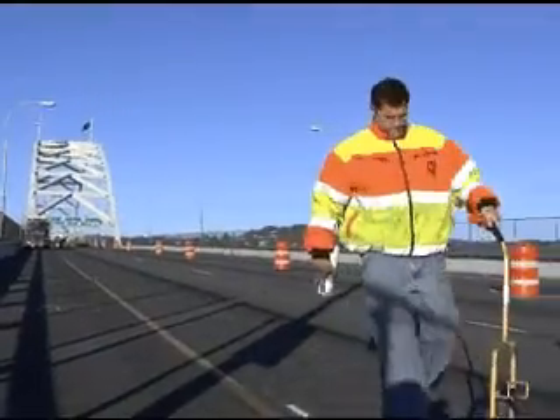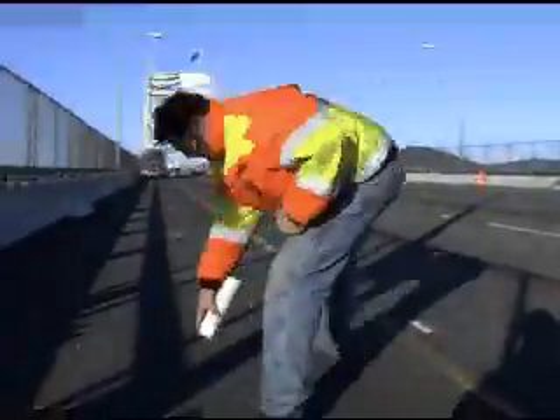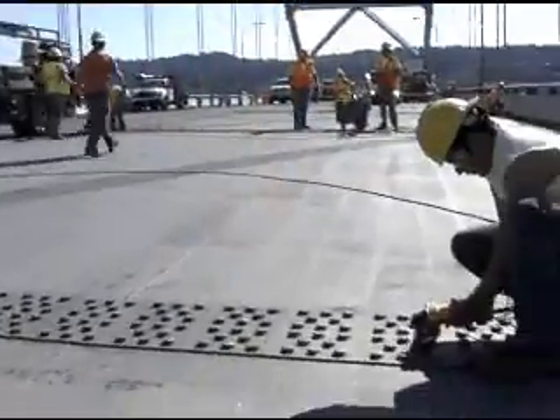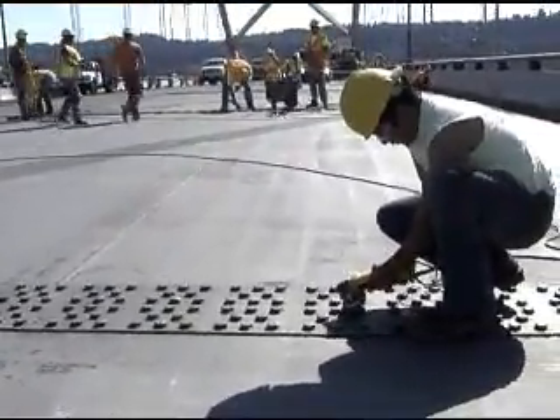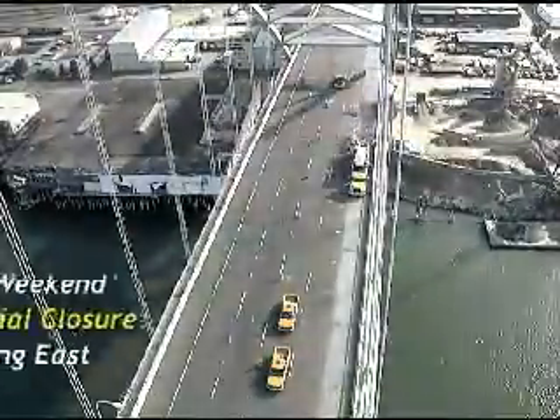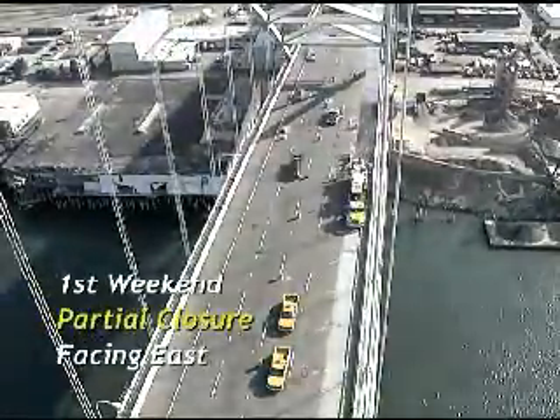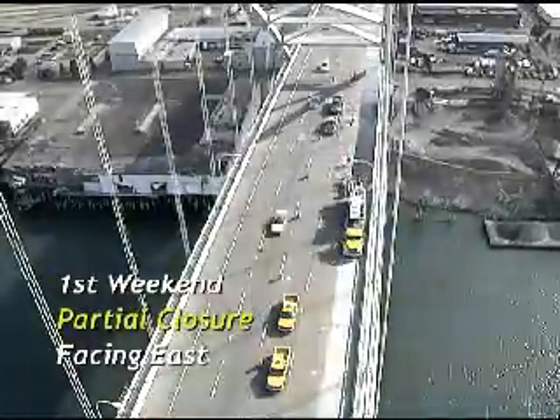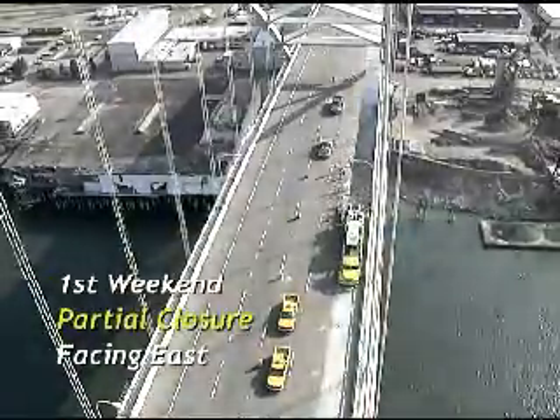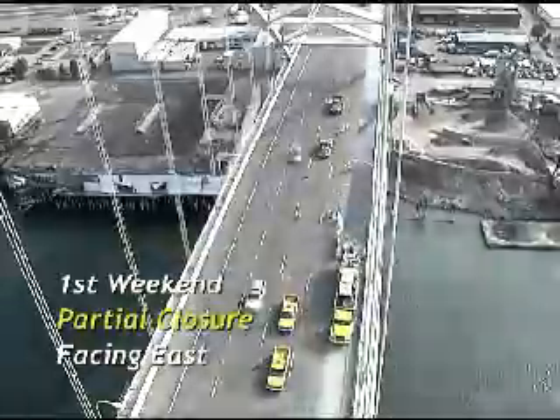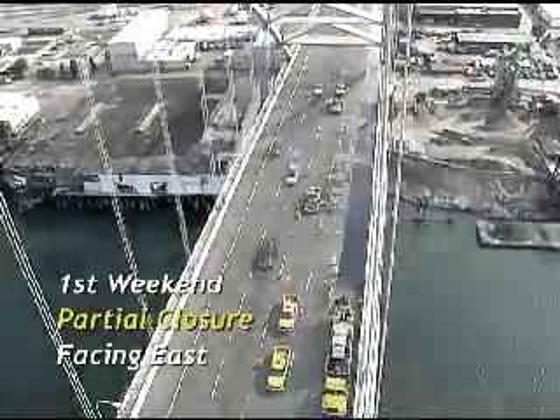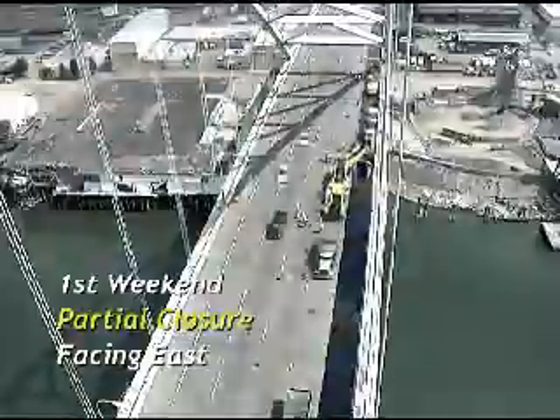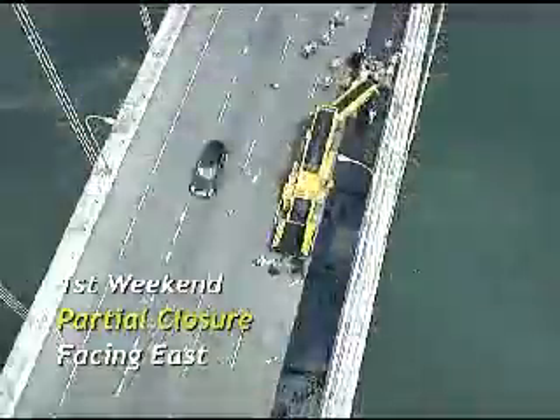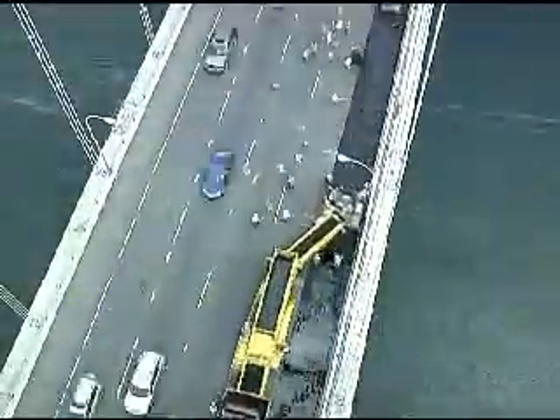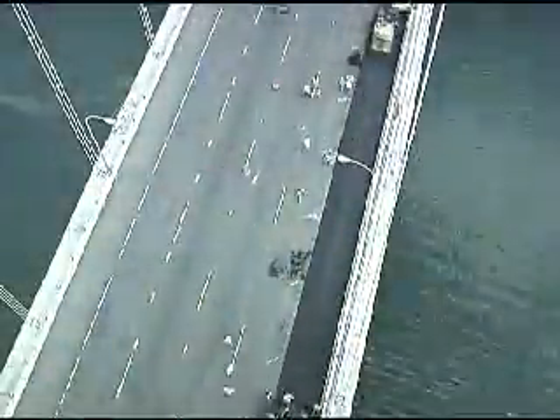The top deck of the Fremont Bridge is what's called an orthotropic steel deck. It consists of half-inch thick steel plate with ribs underneath it. The orthotropic steel plate looks similar to cardboard in that it's got a flat panel on top and corrugations underneath it. And that's what carries a majority of the load of all the traffic that drives across the top of the deck. On top of this steel plate is a layer of epoxy asphalt with another thin layer of regular asphalt on top to serve as a wearing course that could take the damage from studded tires and heavy truckloads and could be replaced easily.